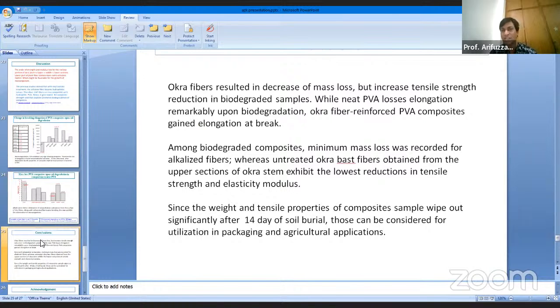So we've seen that different types of fiber show different degradation, and the composite tensile strength and modulus also depend on the fiber treatment and the portion, upper portion, lower portion, and middle portion of the fiber. But all the fiber composites go through degradation after 14 days. So we can say that the weight and tensile strength properties of the composite sample are wiped out significantly after 14 days of the soil burial test. Those can be considered for utilization in packaging and agricultural applications.